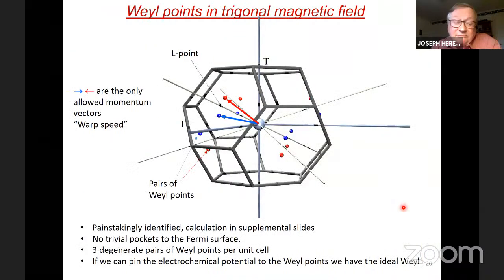There they are. I have here a little drawing. The C-axis is here. The magnetic field is aligned with this C-axis, and the Weyl points essentially split along the direction of the magnetic field. There is a little in-plane component, but most of the splitting is along the Z direction. And you end up then with pairs of Weyl points around the L point. And so that means there are six L points, there are six half Weyl points. One is inside, the other is outside the Brillouin zone. So we really have three pairs of Weyl points in this system at fields above one Tesla.